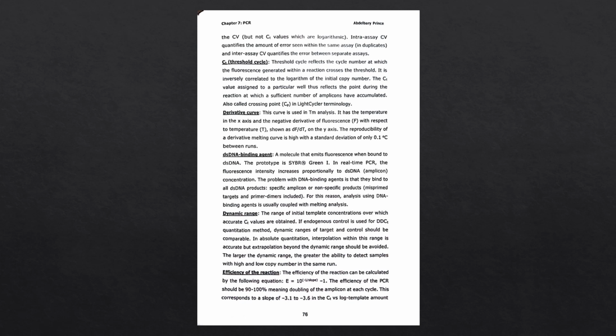Efficiency of the reaction. The efficiency of the reaction can be calculated by the following equation: E equals 10 to the power of negative 1 over slope, minus 1. The efficiency of the PCR should be 90 to 100%, meaning doubling of the amplicon at each cycle. This corresponds to a slope of negative 3.1 to negative 3.6 in the CT versus log template amount.